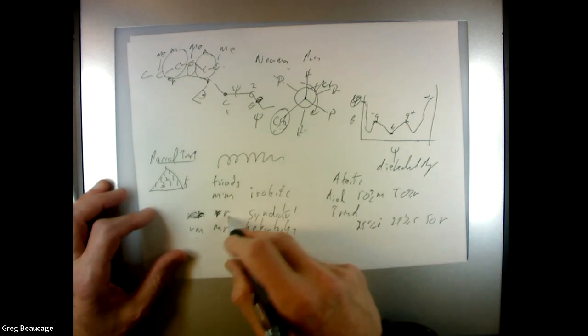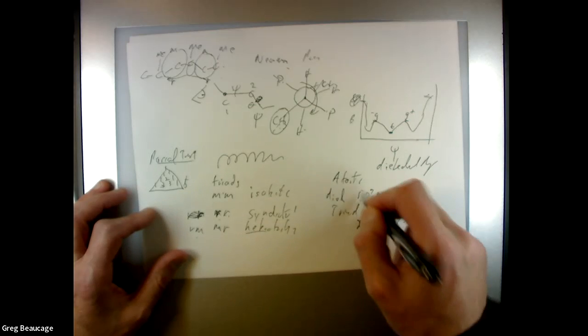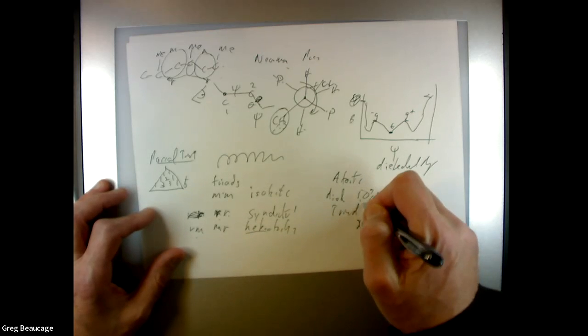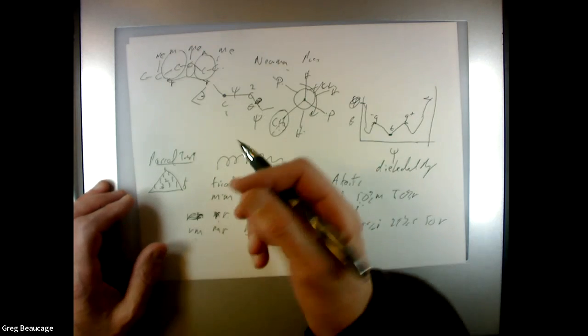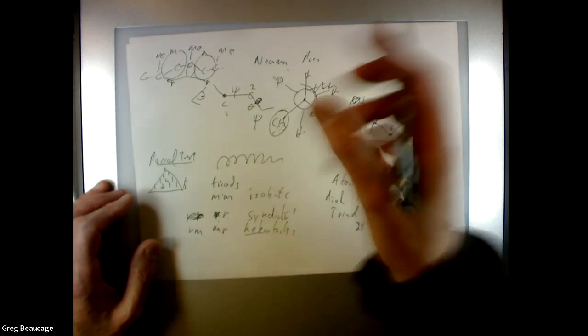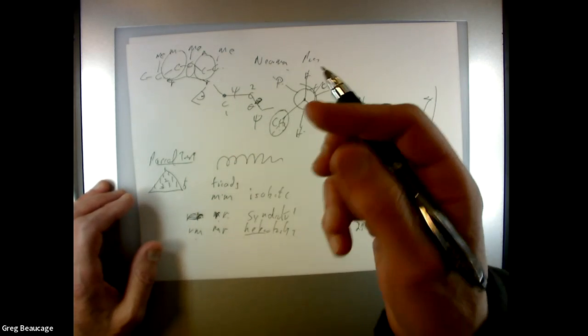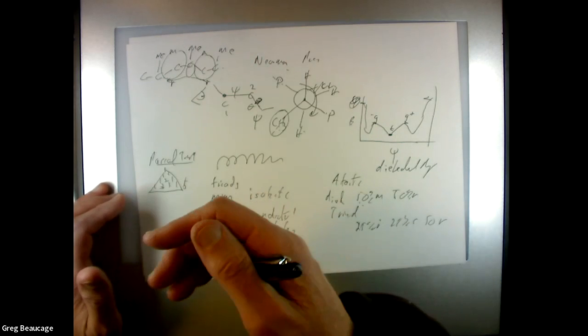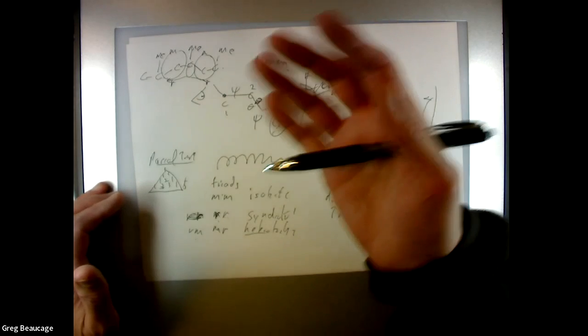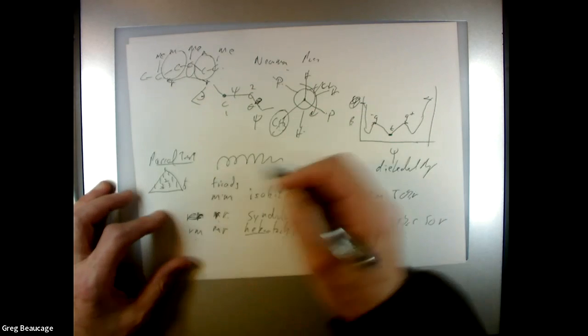Dyads aren't going to do you much good, because you could have a 50-50 block copolymer, isotactic and syndiotactic, that would be 100% crystalline. Or you could have a 50-50 racemic meso atactic polymer that's totally amorphous because it's mixed. So it depends on the distribution. The distribution you need depends on what you want to know.